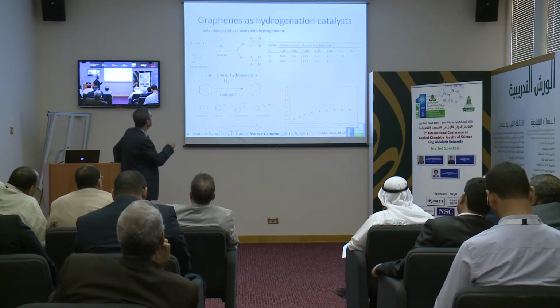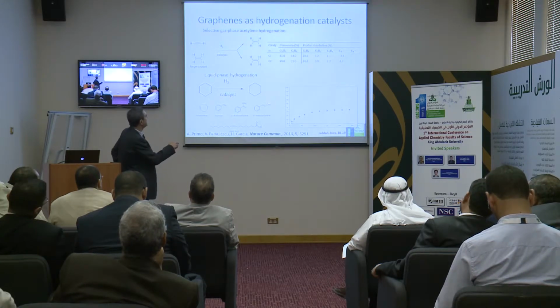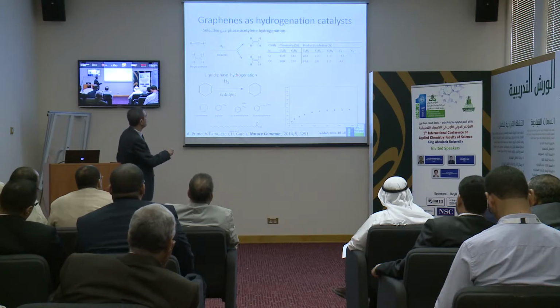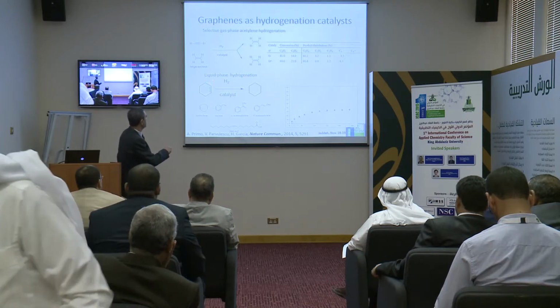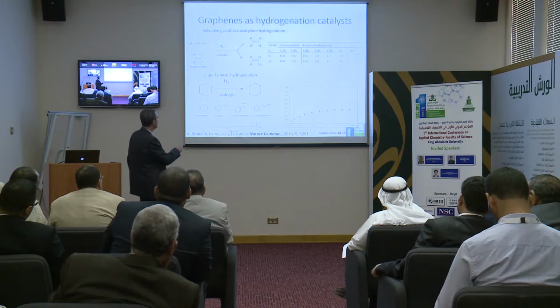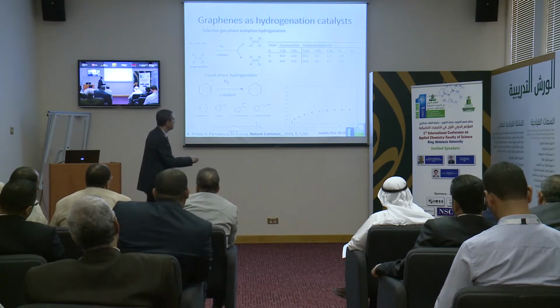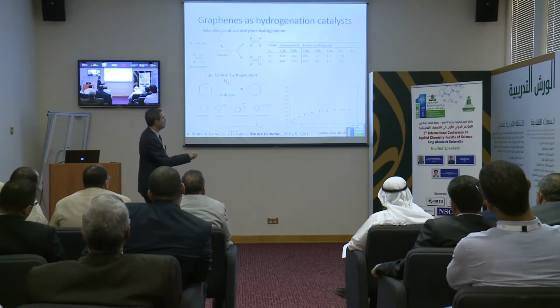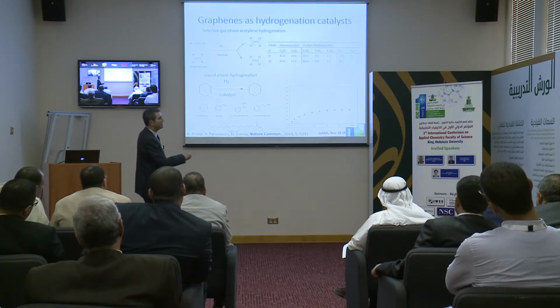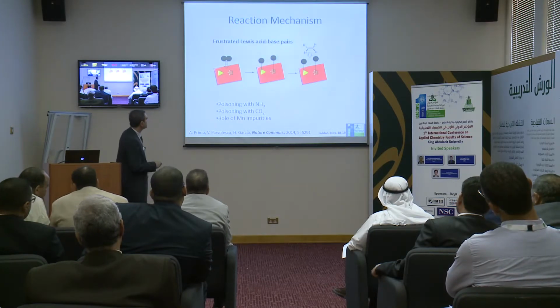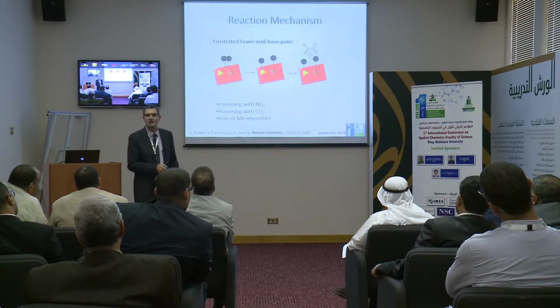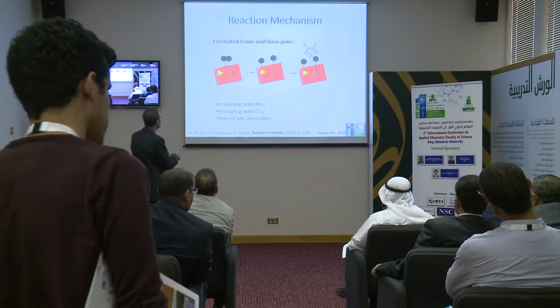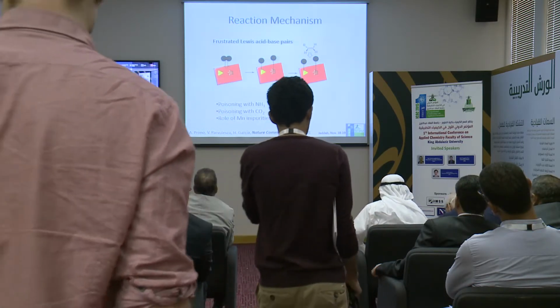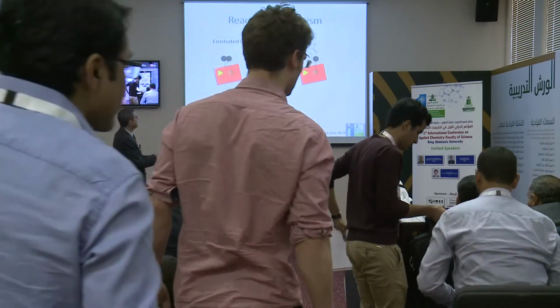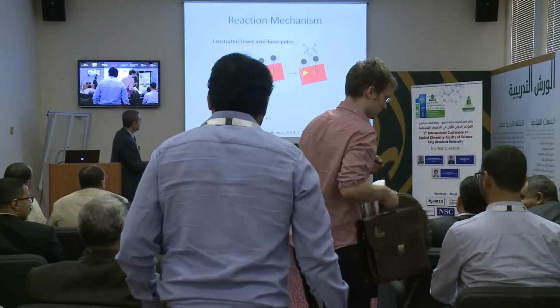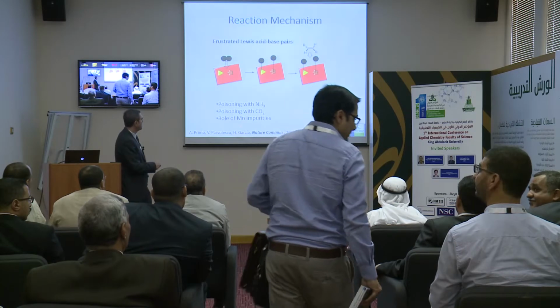Of course, graphene can also promote the hydrogenation in liquid phase. This was gas phase. In liquid phase, we have alkenes like cyclohexene, cyclooctene, and this is a time conversion plot showing that we are able to hydrogenate different alkenes in the liquid phase. And this is the reaction mechanism that we think. So what we need is an acid-base pair, and we activate hydrogen in that way, and we have determined what is the role of impurity in this case.